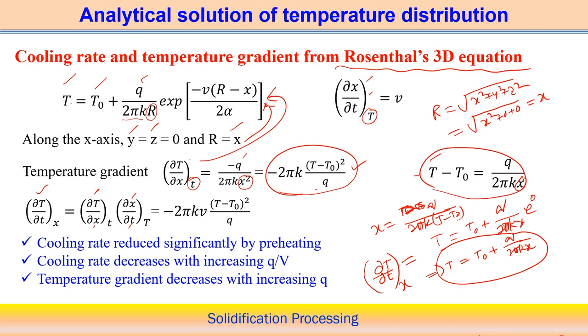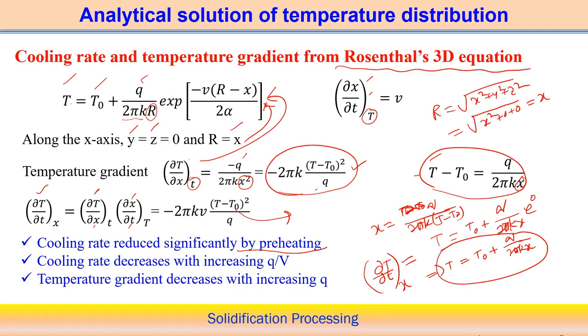Now from the expression, what we can conclude is that the cooling rate reduces significantly by preheating. By preheating, I mean T0 is the initial temperature, so if we heat the material initially, the T0 value will increase, and therefore the T minus T0 gap will reduce. So the cooling rate is reduced. Simply, by increasing the value of T0, or in other words by preheating the sample before welding, say to 300 to 400 degrees centigrade, the temperature difference is reduced and the cooling rate reduces. That is the effect of preheating.